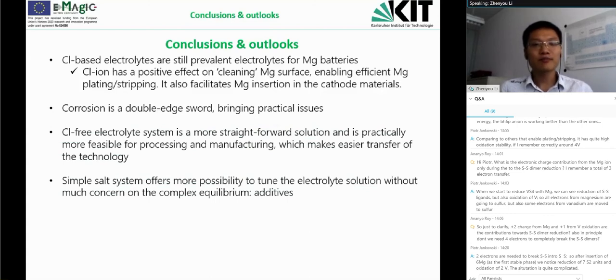We know that even in the case of the lithium-sulfur battery, we have to rely heavily on an additive, lithium nitrate. But in the case of the magnesium-sulfur system, we are still looking for a proper additive that could at least extend or prolong the cycling with the sulfur cathode. But I mean, the chlorine-free, simple salt electrolyte system is definitely a good benchmark from which we could further develop or tune the electrolyte properties and the compatibility with different cathode materials.